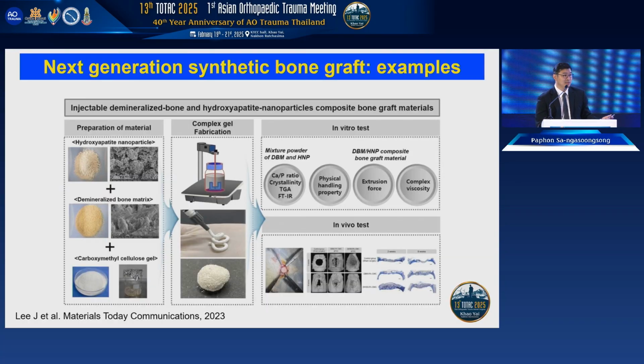So now they try to develop a new or next generation of synthetic bone graft. Until now, there is science using new technology like nanoparticles, inventing nanoparticles of hydroxyapatite, and found successful stimulation of osteoinductive property. So nowadays, synthetic bone graft tries to move forward to a new generation that uses a combination of osteoinductive material and osteoconductive material invented through nanotechnology, and in vivo tests show success and comparable efficacy with the autograft. But I will not talk about this now because the study is still limited.